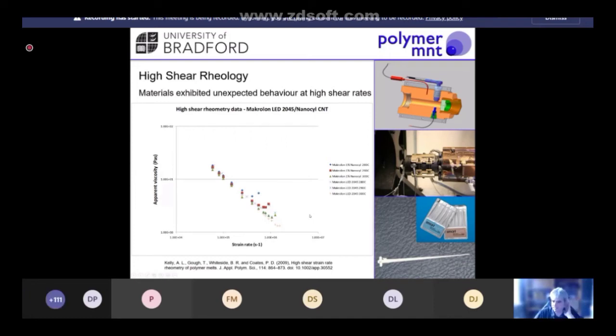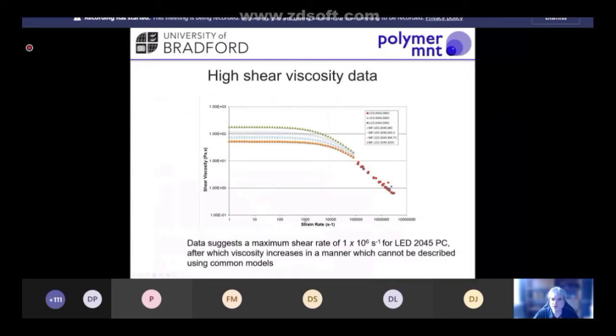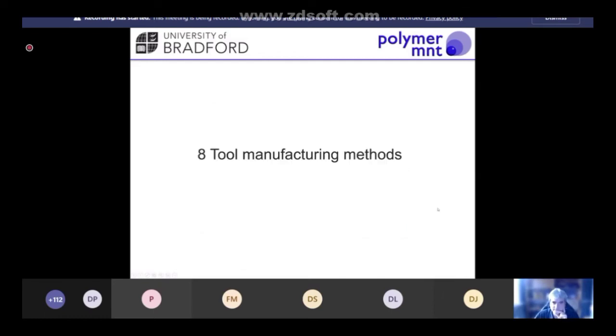So we do lots of screening tests in the background to make sure that our material and process combination is going to work before we actually start creating the manufacturing process. Other examples here: we find that most polymers exhibit a really nice shear thinning behavior, so they flow more easily as you inject faster. But then at a certain point, we get this upturn where the polymer stops flowing. We can get significant shear heating, and that could cause damage to our active pharmaceutical ingredient.